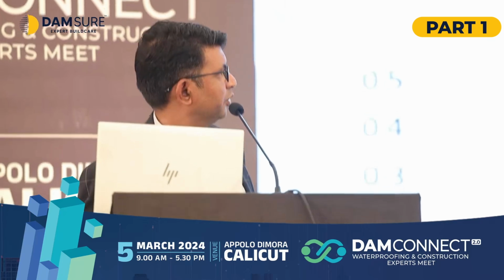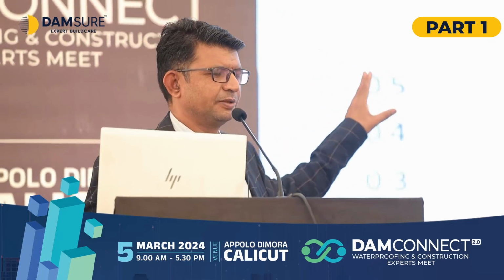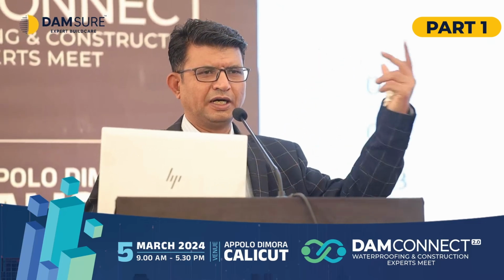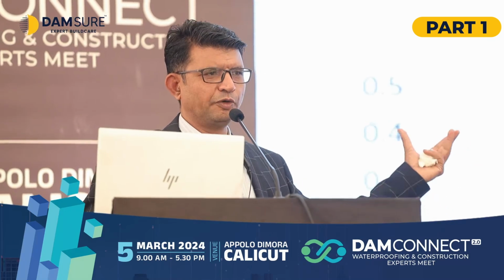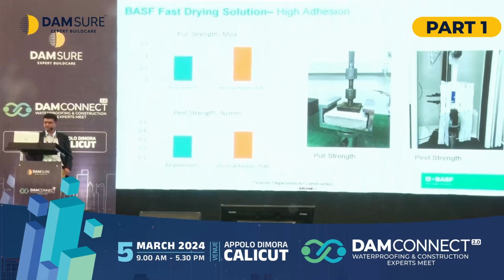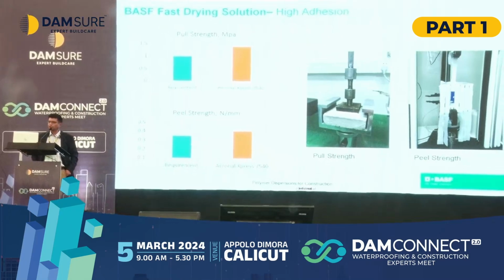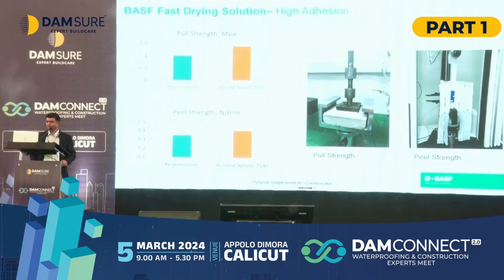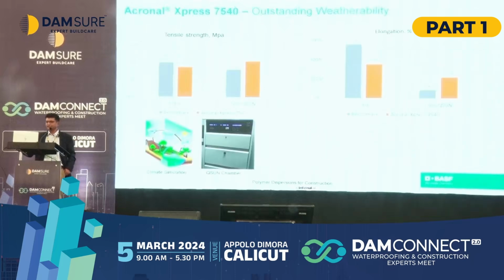Now if you talk about the performance properties, this is the product name on which these coatings would be formulated. Here you can see the pull-out strength is quite good compared to the standard requirement, which normally talks about 0.8 to 1 MPa. The peel strength is also higher. Then you can see the tensile strength and elongation properties. After QUV exposure, you can also see the retention is quite good.